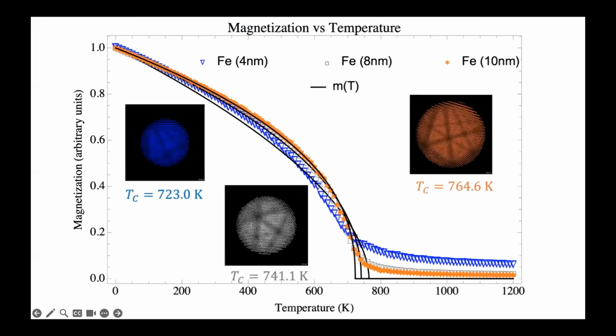When you look at the properties of the magnetic nanoparticles, first we look at the magnetization, and we see that from the 4 nanometer to the 10 nanometer spherical nanoparticles, as the size increases, the Curie temperature increases as well.